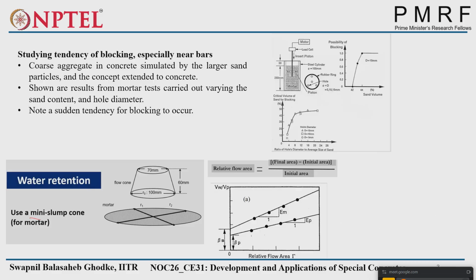So if you see the volume of water to the volume of powder. We saw powder in the last lecture also. Powder means not only cementitious parts, but cement plus fly ash, silica fume, or any other supplementary cementitious material or mineral admixture. Together, it is called powder content. So we plotted the graph of the volume of water to the volume of powder versus relative flow area, and we got this type of linear lines. So can anyone tell me what this beta P and beta M indicate? You just have to find out.